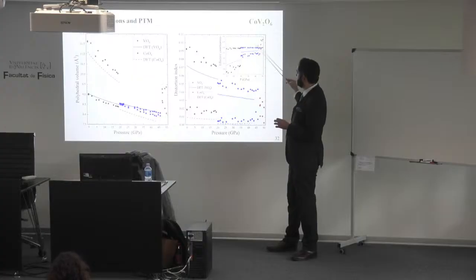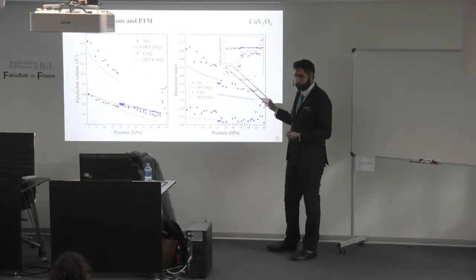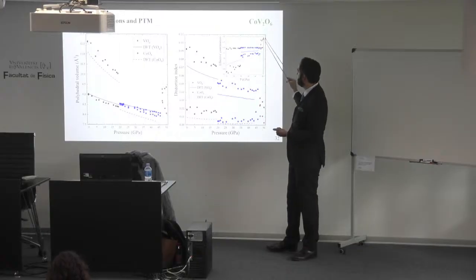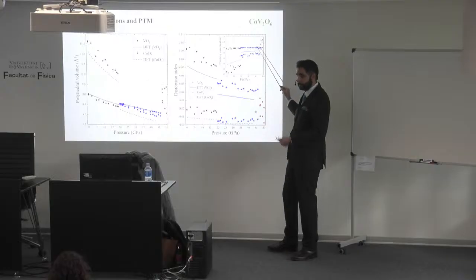And then the last phase transition was also resolved with single crystal methods, and it gets another oxygen into the octahedra, so now it's 7-fold coordinated.